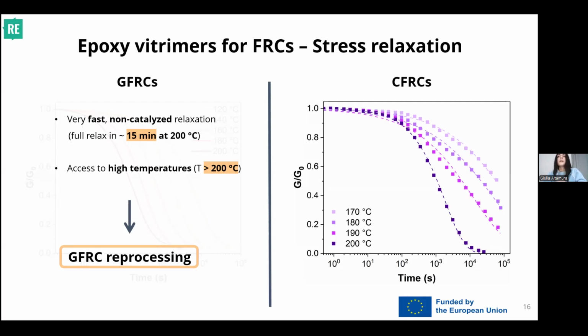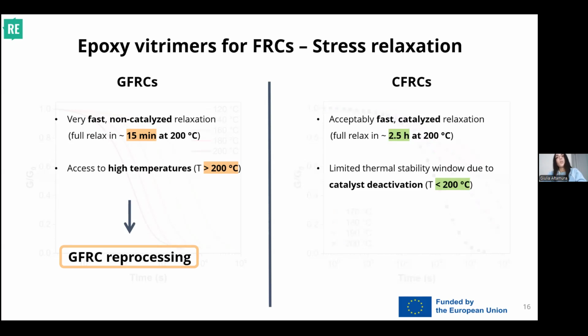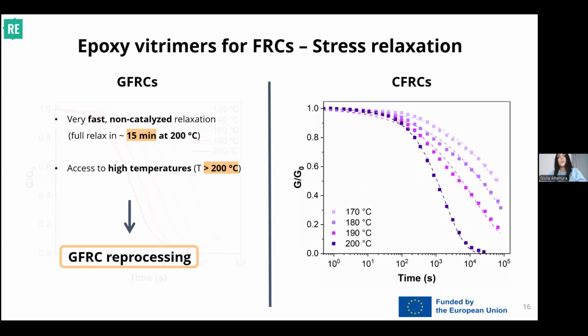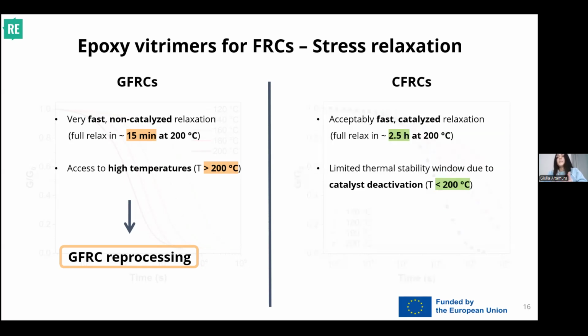On the other side, instead, we can see that relaxation is a bit slower. At 200 degrees, we get full relaxation in only 2 hours and a half. However, I let you notice that the curve at 200 degrees is a bit different in shape with respect to the others, and this could be a hint of something occurring inside the material, possibly, maybe, catalyst deactivation, since TBD is pretty sensitive to high temperatures. Therefore, we decided to create a carbon fiber reinforced composite with this material to reprocess it by recycling it, but staying below this temperature.